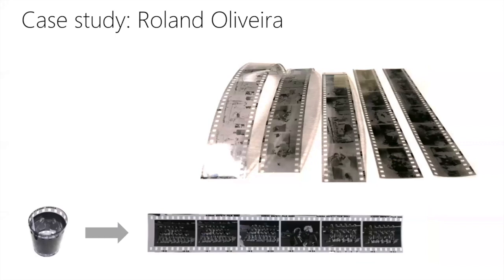Here you can see the first tests we made with different times of exposure to the vapors chamber, and the final results obtained for one strip before and after treatment at the bottom of the slide. So the treatment applied here was 24 hours in the vapors chamber and 48 hours under weights.